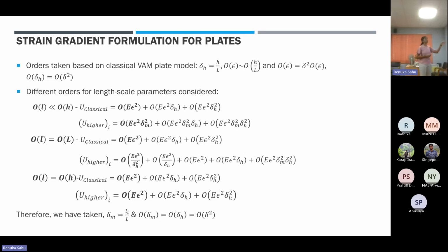Again for plates we have analyzed different orders of the length scale parameters, considering the plate thickness instead of the beam width as for beams. In the first case, the material length scale parameter order is much less than the order of the plate thickness, giving similar behavior where the higher order energy is of higher order than the classical strain energy. For the material length scale parameter equal to the length of the plate, we get a lower order of strain gradient strain energy. For the same order as the plate thickness, both energies have the same order. We have taken this particular case and moved forward with our formulation.